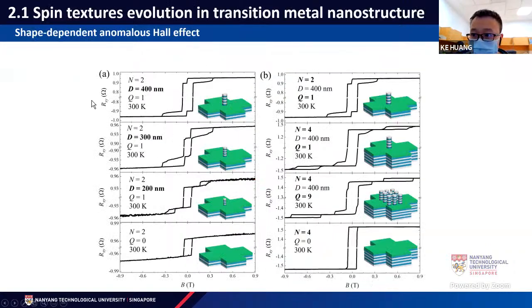And finally, we measured the anomalous Hall effect with different nanostructure shapes. So firstly, in this column, we decrease the diameter of the nanodisk. And even if it's as small as 200 nanometer, this skyrmion bubble region is still there. It's unchanged. Although it becomes smaller, it's still there. It's very stable. And if we increase the number of the nanodisks,